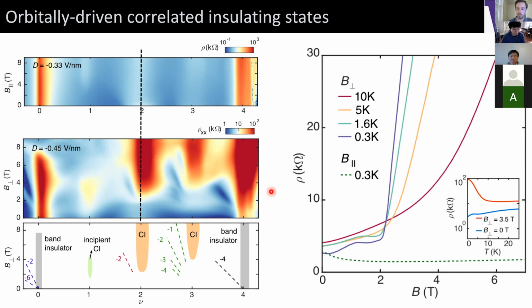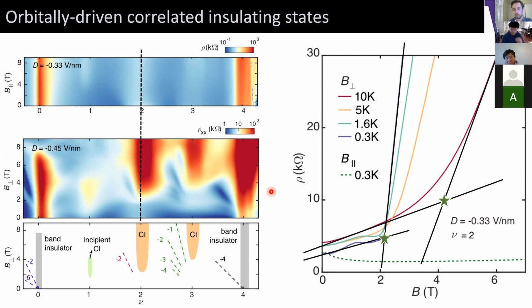So we can characterize this a bit by basically fitting some sort of critical field, which we're just going to define as the crossover point between linear fits to the low field and high field magnetoresistance. And so these start points are what we want to call some sort of critical field, where we expect something like a first order phase transition between a metallic and an insulating state.